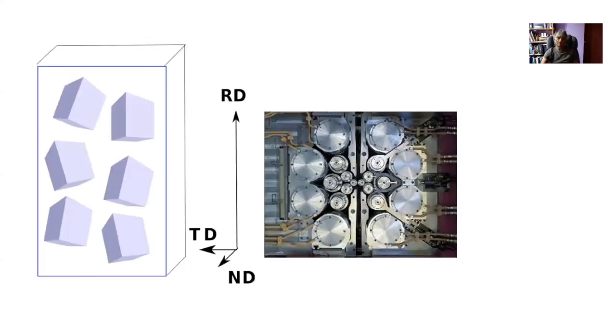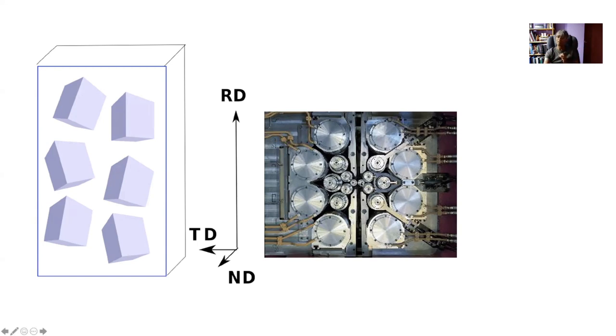In a polycrystalline material, many crystal orientations are present. In a rolling mill making extremely thin stainless steel sheet for razor blades, small-diameter rolls are backed up by larger rolls to maintain rigidity and produce a parallel-sided strip. The rolling direction, normal direction, and transverse direction define the sample geometry. As the polycrystal deforms, slip planes and slip directions tend to align with the deformation directions.